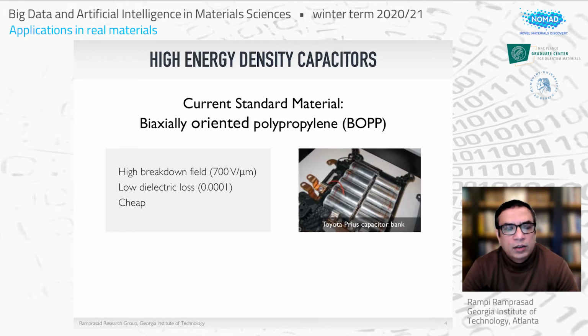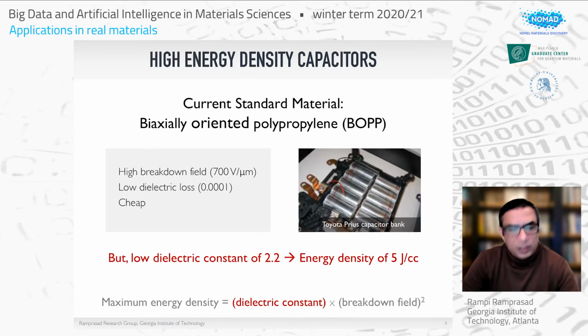And it's a great, remarkable insulator. It has a big band gap, which translates to a very large breakdown field. Meaning this is the highest electric field that the material can withstand before it breaks down, right? 700 volts per micron. It has a very low dielectric loss. And what that means is that pretty much all the electrostatic energy you put in, you will get out, right? The dielectric loss factor, loss tangent is 10 to the minus 4, which is a remarkably low number. But there is a problem.